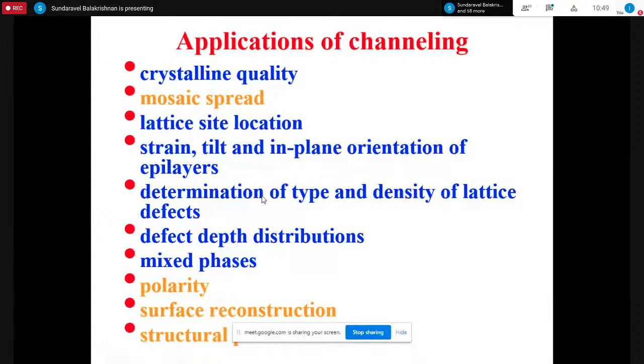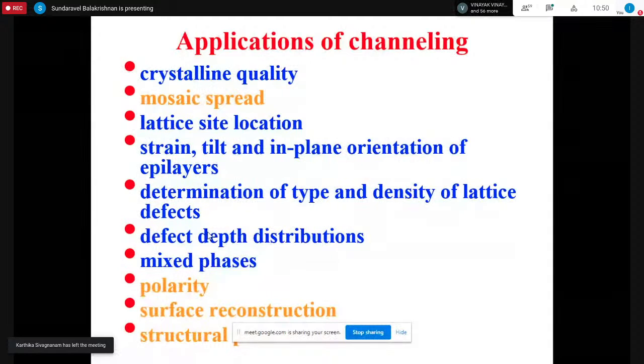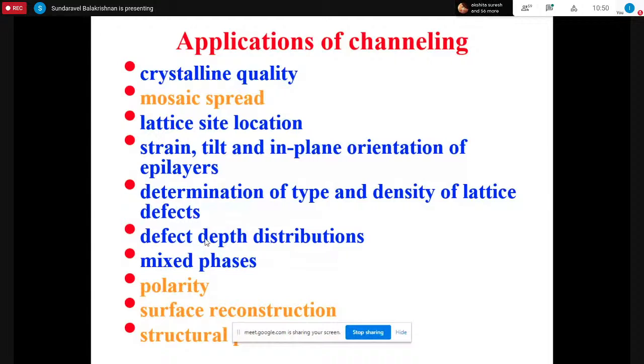But point defects here, I mean only the interstitial defects, not vacancy defects. Only interstitial defects it is sensitive to. And for vacancy, one has to go for positron annihilation techniques. And one can determine whether mixed phases are there or not. For example, if you take gallium nitride, there can be cubic and hexagonal phases, and it is possible to do with XRD.